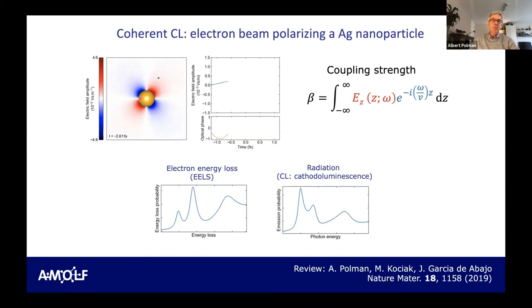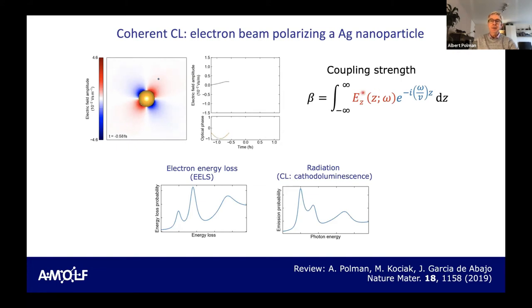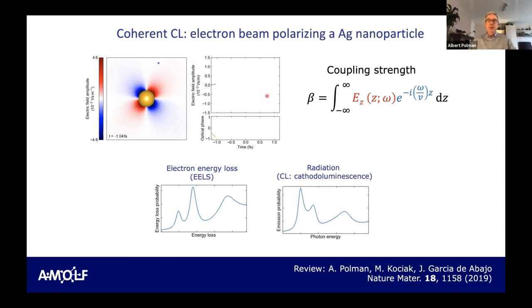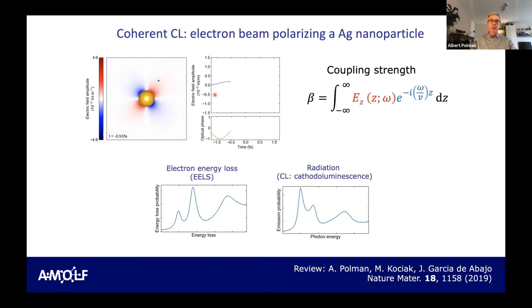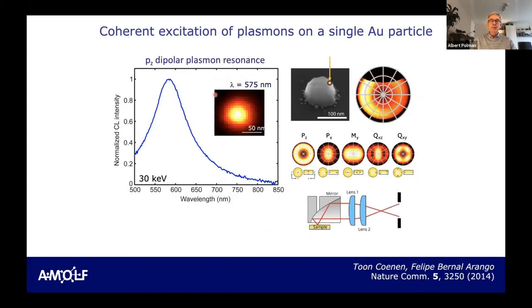At the same time, this particle will radiate into the far field — the dipole moment radiates, and that's called cathodoluminescence. Both EELS and CL happen simultaneously. The probability for this to happen is the integral over this curve — the integral of the electric field over the trajectory of the electron, which is slightly non-zero, creating the EELS or the CL spectrum. That's a classical description, but ultimately it's a quantum mechanical phenomenon: the electron either loses energy or it doesn't, and the probability is given by that classical calculation.